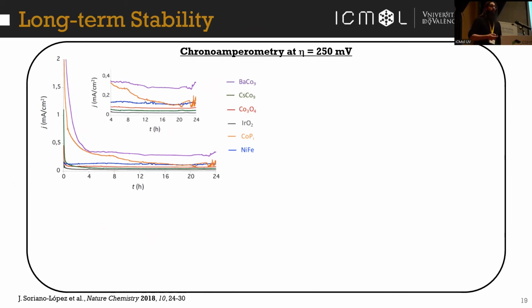The CoPi catalyst, or Nocera catalyst, is analogous to cobalt oxide, which is probably the most active material under neutral conditions. And we can see it was pretty active for the first 8 hours, but then it slowly decomposes. And we also compare it with the nickel iron spinel, which is one of the most active materials under basic conditions. And yeah, basically it was stable as well, but not so active.